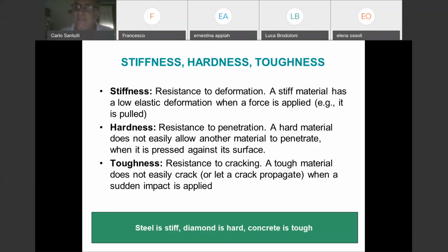Concrete is tough. Concrete and many ceramics are tough in the sense that you have a crack, which means an obvious defect, a visible defect. You have a crack, but this crack doesn't grow, doesn't develop for many, many years in some cases, and doesn't bring to failure the material. In reality, what happens with concrete is not the problem of cracks. Concrete leads to failure especially in terms of fatigue forces. If the force is always the same, think of the concrete bridges. If the force is always the same, so the bridge withstands its own weight, no cars passing, the cracks can stay there for many, many years.